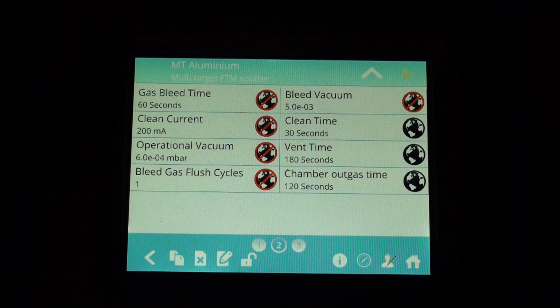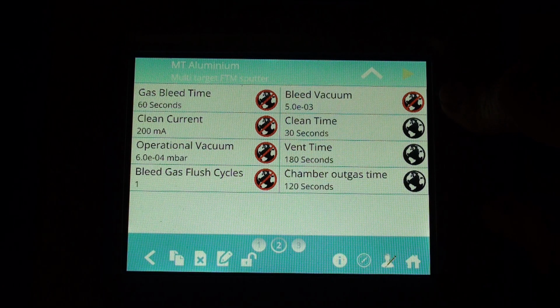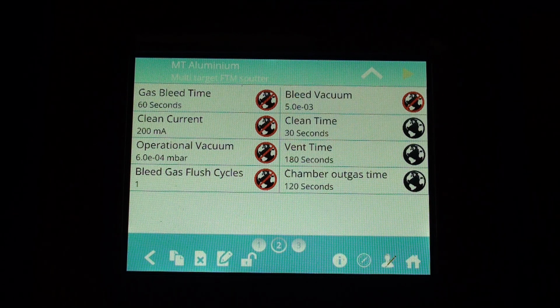Operational vacuum you don't play with. Bleed gas flush cycles, you can increase that. I generally only do one. Bleed gas vacuum, that is what I consider to be the optimal pressure to backfill with argon to get high quality aluminum coatings. Cleaning time 30 seconds, that's default. You may want to increase that. Vent time and chamber outgas time are pretty much factory set.